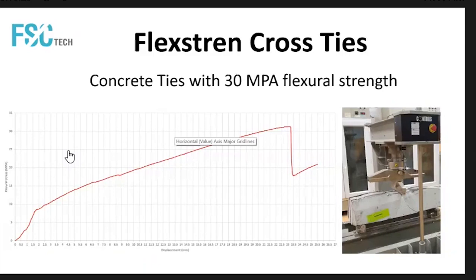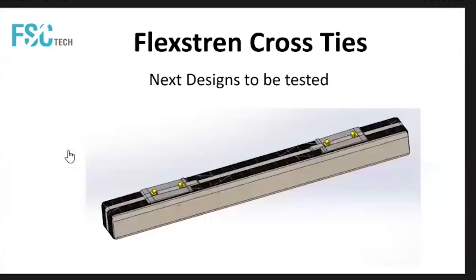As you see, the behavior is relatively different from what happened on a steel reinforced tie. You can see the first section where you have a stiffness that is more or less the same as a pre-stressed tie. Then you have a crack. Then the stiffness becomes one third, and you have a failure with an enormous deflection. That is what we are going to make, basically.